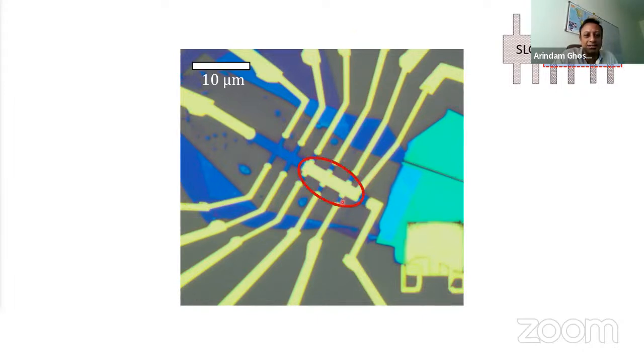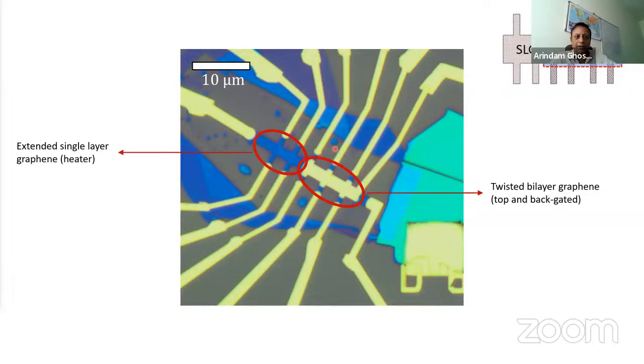And you can see that this layer is underneath this, you have the twisted bilayer region. And for thermoelectricity, we need a heater region. And for that, we need this part, which comes out a little bit. And this is a single layer region. So the lower one is the full one, and then an additional layer of another graphene, which is rotated by about 1 point some degrees, is kept on top. So this is how most of our twisted bilayer graphene devices are created.